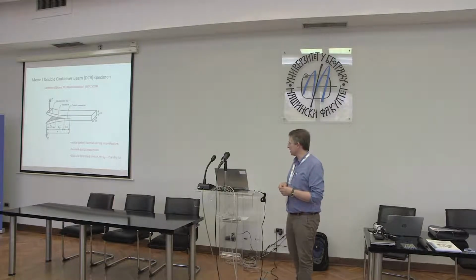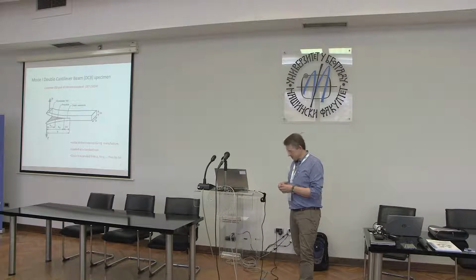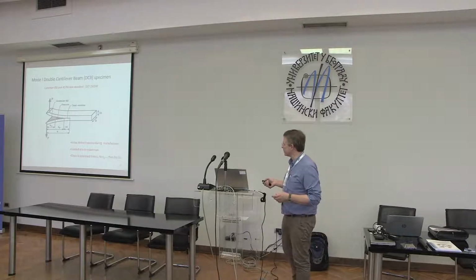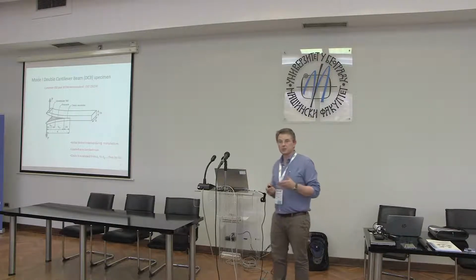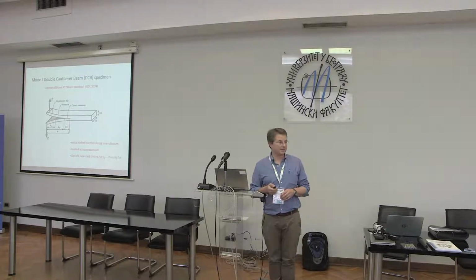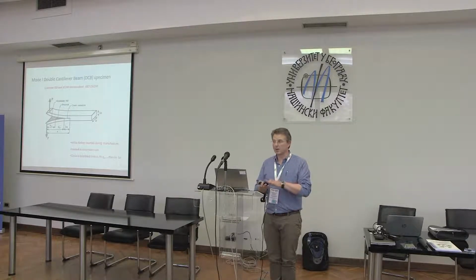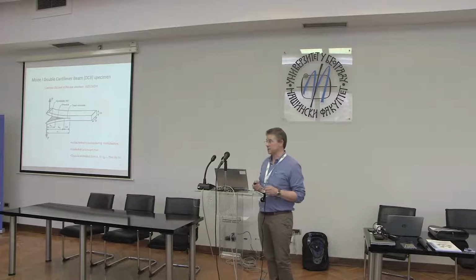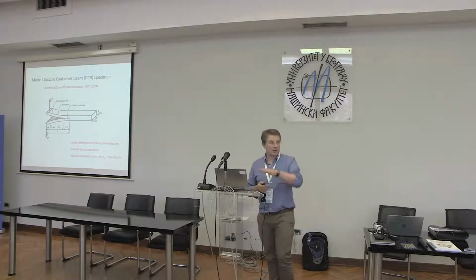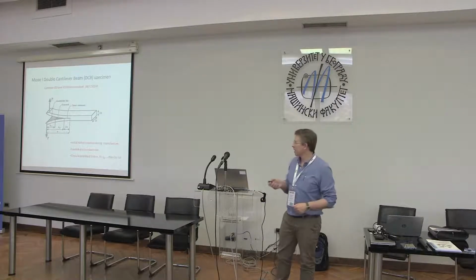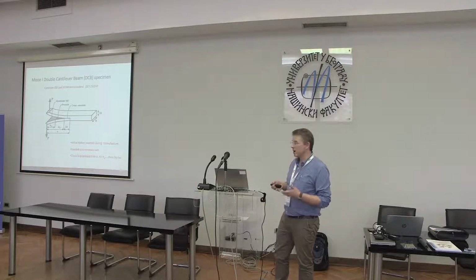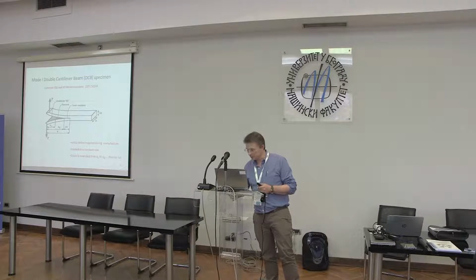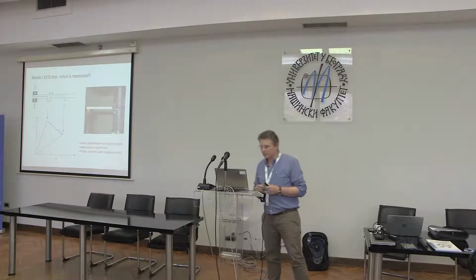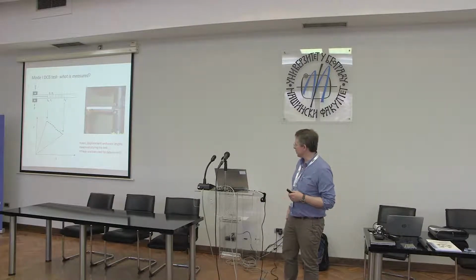So we embed typically, it says aluminium foil in here, but that was used originally. What we tend to do is embed a sheet of PTFE film in between the two laminate layers on the mid-plane of the specimen whilst we make it. Then we cut the specimens out, and you can attach end blocks, and you've got a fracture specimen with a ready-made crack in the middle. And this is how it's realized.